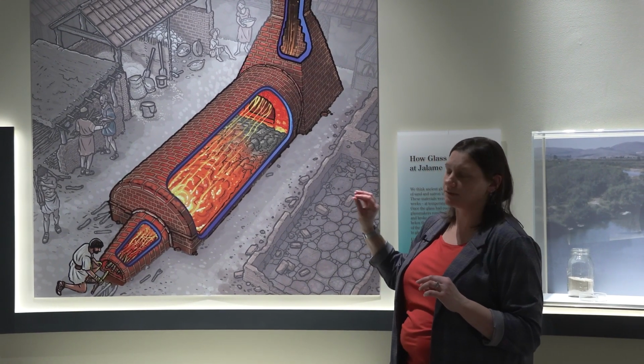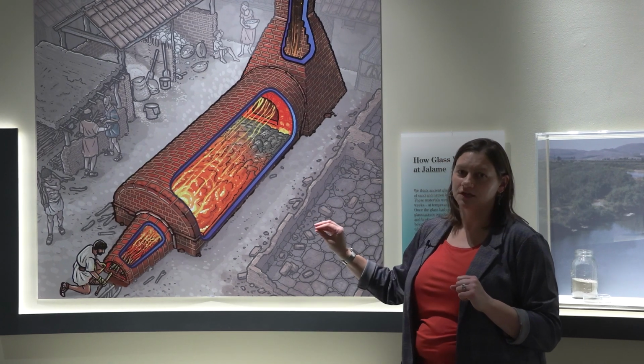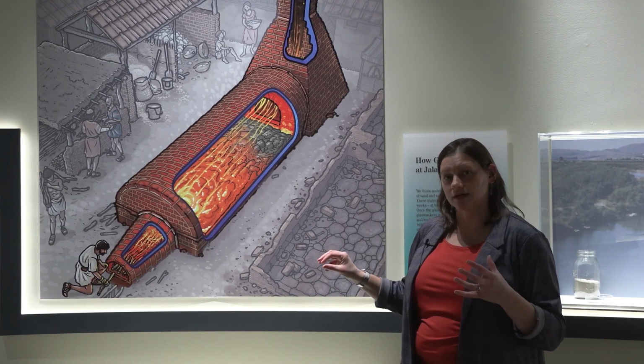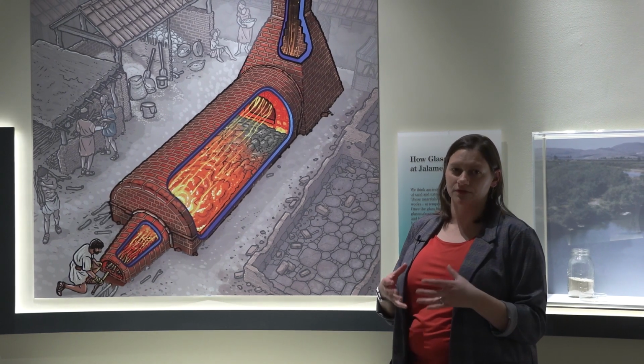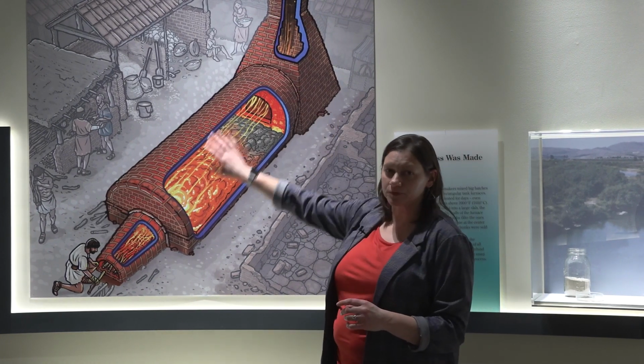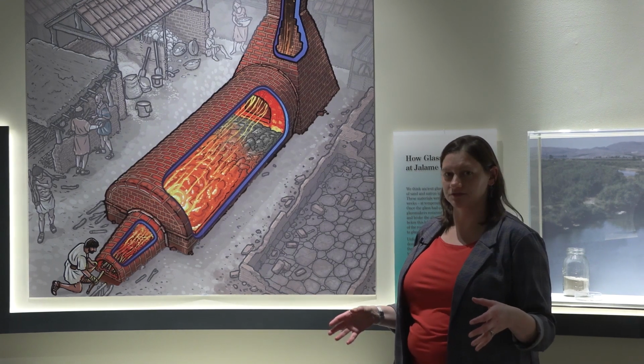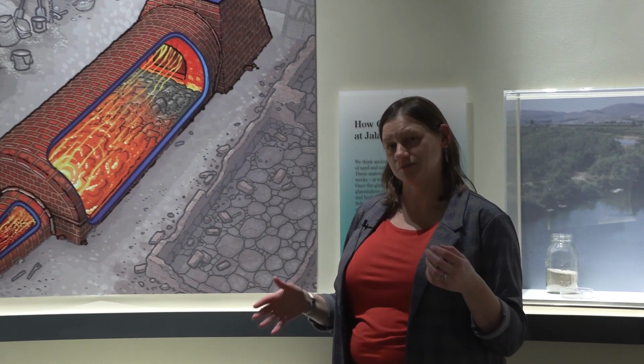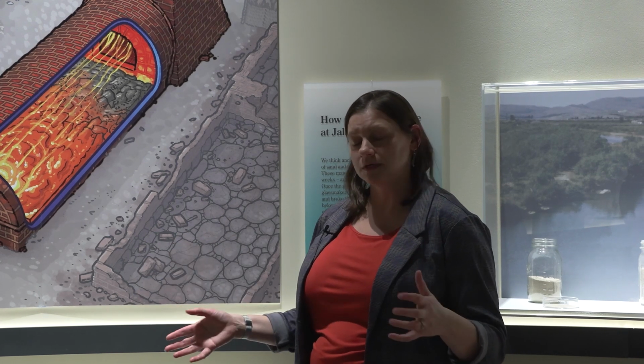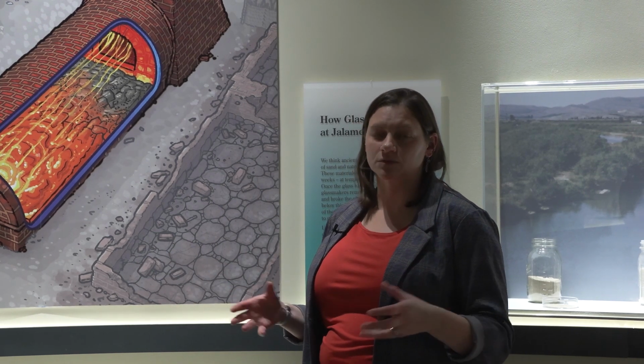So those materials would have been mixed up and then fired in these furnaces for days or even weeks at a time to basically cook those materials together to form the glass. And then this entire superstructure was disassembled, was taken apart. So that's one of the reasons we don't have really any of those that survive. We just have those foundations. And the glass, which would have been left behind in this big sort of slab, was then broken up into smaller pieces where it could then be shipped out or sold to glass workshops throughout the Mediterranean and the rest of the ancient world. So another question that people ask pretty regularly is how glass gets its color.